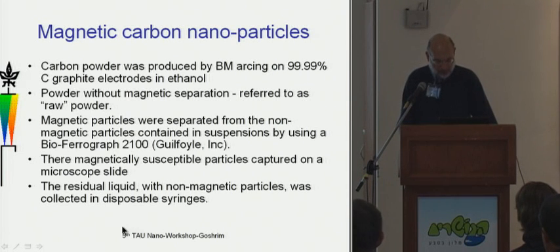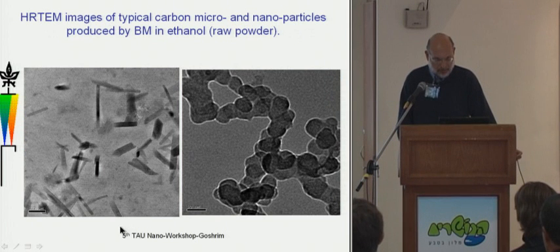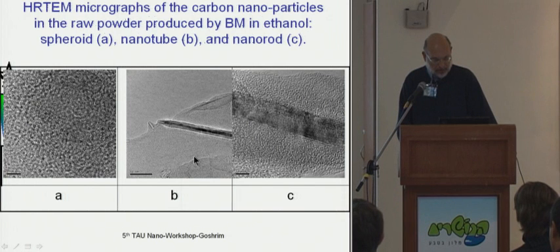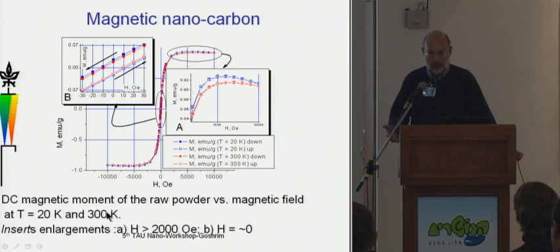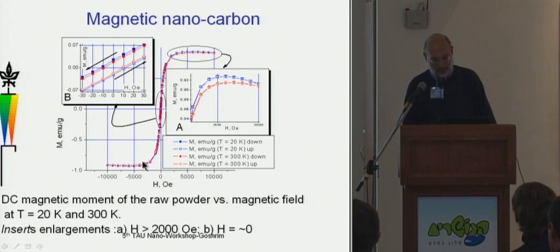And then we did two things. First of all, we looked at just the particles collected in the raw powder, and there's all different kinds of particles. And second, we took the raw powder because we could get a sizable quantity of it, and sent it to a colleague at the Weizmann Institute, who put it in a magnetic measuring device to measure the magnetic properties of the raw powder. And surprisingly, we found that indeed this raw powder of nothing but carbon, in fact, is magnetic. It shows a characteristic similar to ferromagnetic materials. By that I mean it has a saturation region at high magnetic field. You can kind of see it here, and some degree of hysteresis.